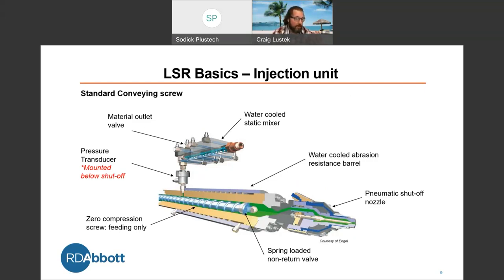Looking at your LSR basics for your injection unit, you're looking at a standard conveying screw where we have a material outlet valve. We've got a water-cooled static mixer. And again, that static mixer is there to help slow the vulcanization process, the cure process of that material once the A and the B come together. We have a pressure transducer mounted below that shutoff, and that is an option, but it is a process aid. It can help you with your process. If you can monitor during your run, you know what your pressure is at.